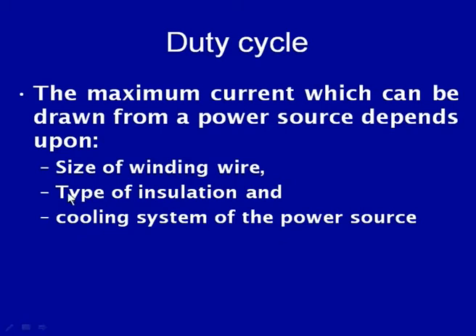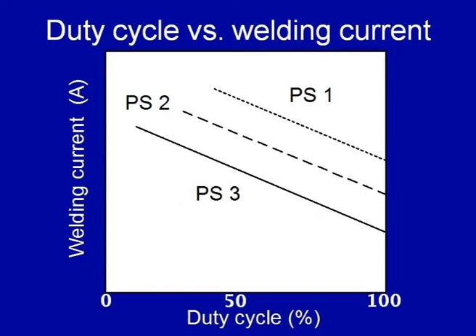So, if the cooling system is effective, if the insulation is good, and the size of the wire is big, which is offering less resistance for the flow of the current, then as a whole, first, electrical resistance heating will be reduced, then the capability of the insulation to withstand the heat will be more, and third, the temperature will be maintained within the limits if the cooling system is effective. So, if these three things are present, then the power source will allow us to draw the higher current, or it will allow us to work at a higher current even with the higher duty cycle. So, in general, if we are drawing the higher current, then we need to work with the lower duty cycle.